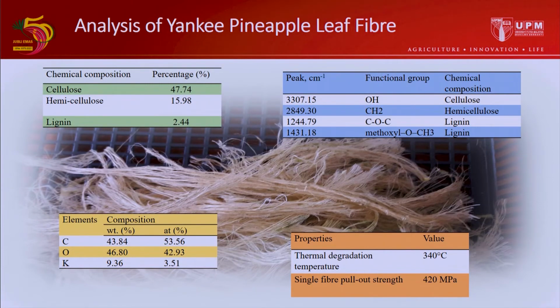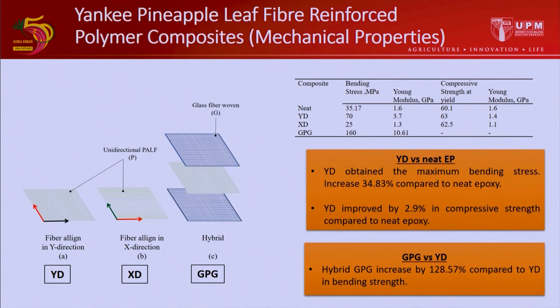and the single fiber pull-out strength is 420 megapascal. The figure shows the composite made from pineapple leaf fibers extracted from the Yankee variant in Teluk Panglima Garang. With the addition of fiber in the epoxy, the composite with fiber in the Y direction obtained the maximum bending stress, which increased by 34.83% compared to neat epoxy.